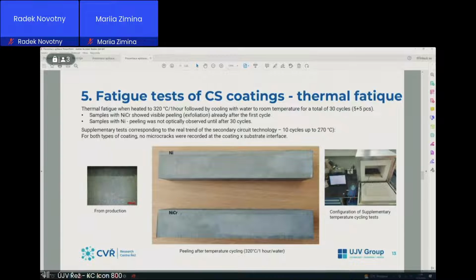Then, as I mentioned, we performed supplementary tests. In these tests, we heated samples to a temperature of 170 degrees, and then up to 270 degrees, and then cooled down these samples. And after 10 cycles, for both types of coating, no micro cracks were recorded. So we can say if an operator will use cold spray coatings on the secondary site of a nuclear power plant, then these coatings should survive, let's say, 10 shutdowns of the plant.